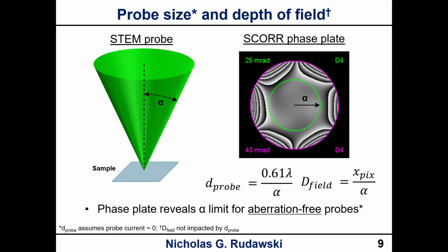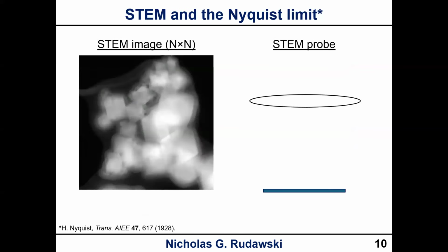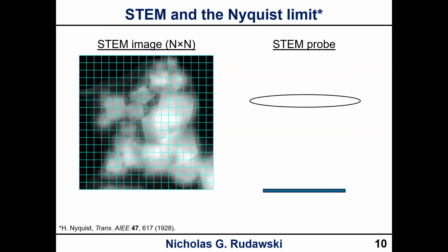You notice, of course, depth of field has no impact from probe size. It depends only on alpha and the physical pixel size of your STEM image. So if we have a STEM image which is square, N by N, we can discretize it. And so we can define a field of view in the x and y directions, which is equal to the physical pixel size multiplied by the number of pixels in either direction. So the physical pixel size is equal to the field of view divided by the number of pixels. And then we can define the Nyquist limit as equal to twice the pixel size.